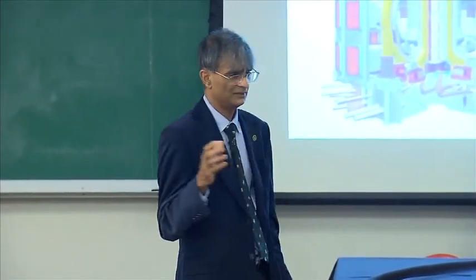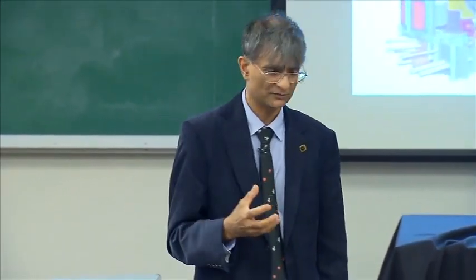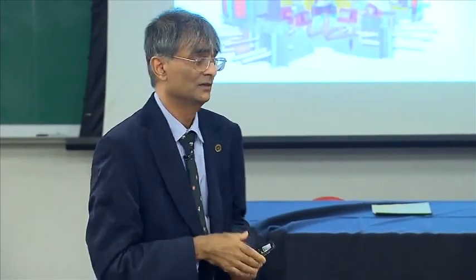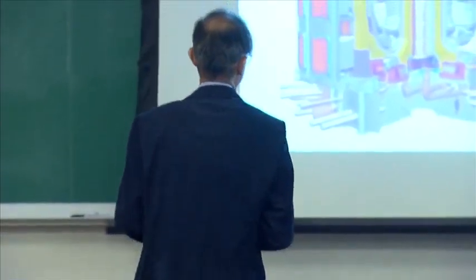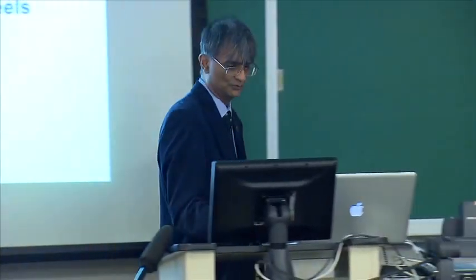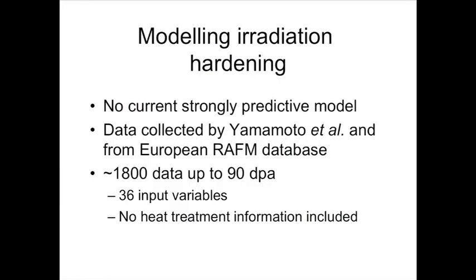But the point is that in about 5 or 10 years' time, there will be an experimental facility which is not a fusion reactor, which will allow very large doses of radiation. But the volume of material that can be exposed to that is quite small. So if you want space in that volume, it's like sending a sample into space to do an experiment. You have to really, really justify that you've done your thinking to do that. So the aim was to model irradiation hardening, okay? And there is currently no theoretical model which can do that, okay?